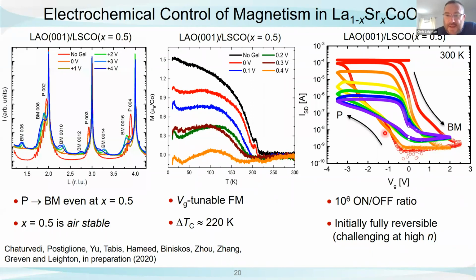And then we can come back and we can rejuvenate this and go back to the perovskite phase, to the ferromagnetic metal, again with a 10^6 on-off ratio. Now, I should emphasize that those previous papers that I highlighted on that slide before showed this happening over a few cycles. We can also do it over a few cycles, but I don't want to gloss over the fact that if we go to a larger number of cycles, we see endurance problems.